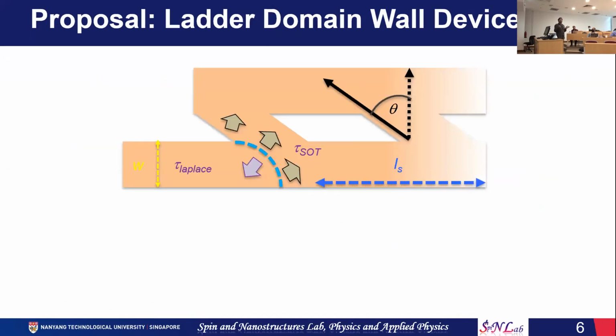So keeping in mind this pinning approach, we basically did a geometrical pinning method and proposed this idea of ladder domain-wall devices. In this schematic, you can see the segments are basically parallel pipes that are connected through these middle segments that are slanted with respect to the normal to the horizontal.